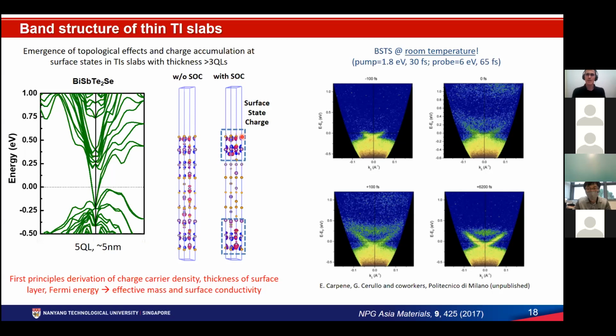But our experiments are made with a crystal that is exfoliated and is done at room temperature. So we were worried whether the surface states were actually surviving in the samples that we are using. We engaged some collaborators in Milan that have time-resolved ARPES, and indeed this shows that BSTS surface states do survive at room temperature. You can see the creation of the surface states that are very clearly defined.